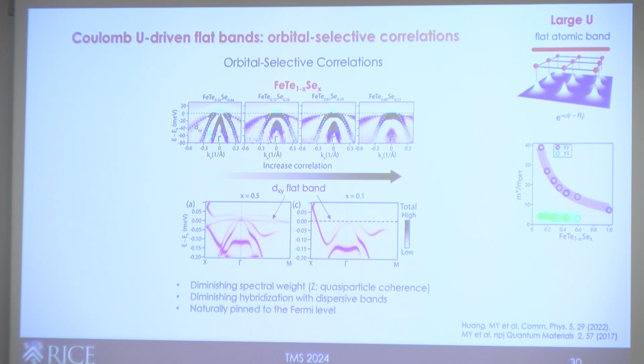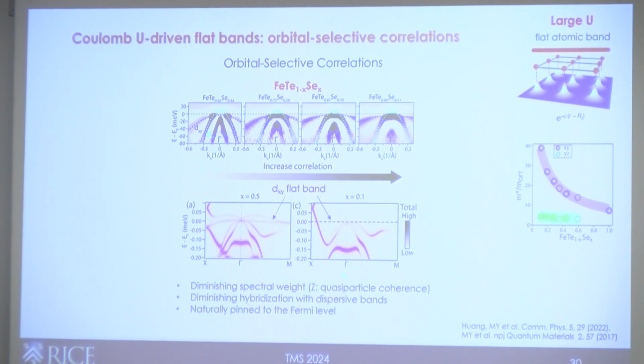This suggests that these orbitals, like Lenny has discussed, actually exhibit orbital-dependent correlation effects. How to capture or understand this is a collaboration, a calculation with my colleague Tim L.C.'s group. You can see that in the strongly correlated regime, this is the XY band. It's already very strongly renormalized near the Fermi level, and it's very faint, but it still has a finite hybridization with other dispersive states. If you keep going towards that end, they can realize a regime, theoretically, we can argue whether that's reached or not. But anyway, from this calculation at least, they actually see a limit where that orbital becomes localized. So it's gone, it's gapped out from near the Fermi level. And then you recover the Fermi surface you would get from the dispersive states.